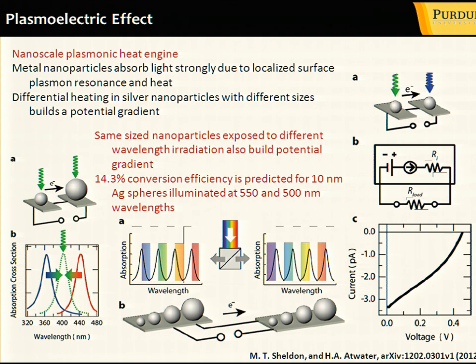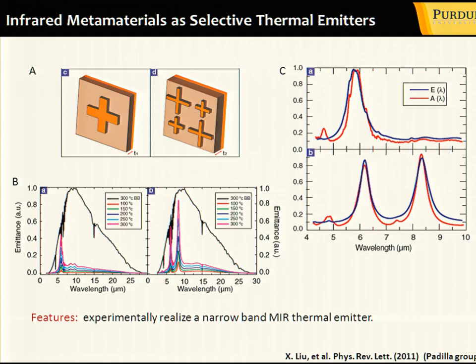Yet another very interesting development in the area related to generation of electrical energy by using plasmonic structures comes from the Harry Atwater group. The idea here is, if you have a couple of plasmonic particles which are different in size, or you could have particles of the same size but irradiate them at different wavelengths, in both cases the heat absorbed by these particles when you excite these plasmon oscillations would be different, and that would result in a gradient in temperature. And because of the thermoelectric effect, you would start generating current. The surprising thing is that the efficiency is actually quite high, above 14%, in these metallic particles. You see, in this particular case, you use these plasmonic structures not to increase the photovoltaic element, but rather to directly generate electricity.